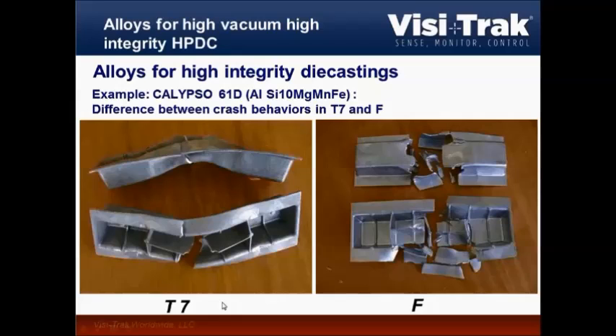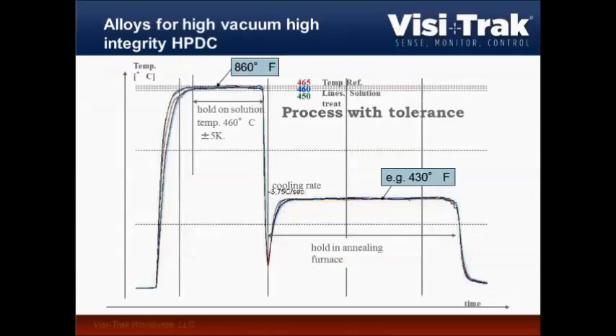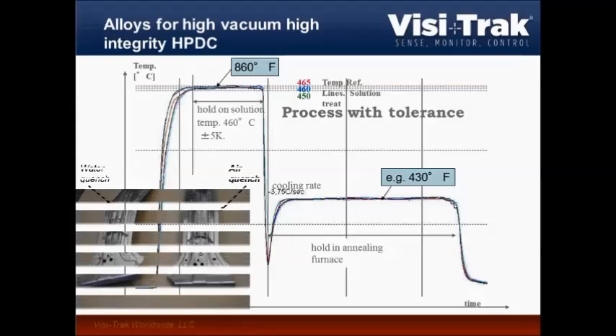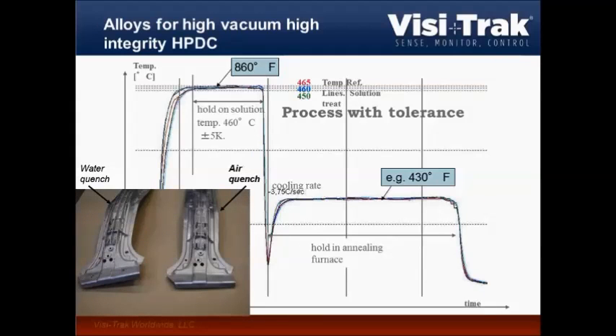They were damaged, but still intact, while the as-cast parts were really scattered into many different parts. So therefore, for safety critical crash relevant parts, it continues to be important that we develop proper heat treatment recipes that include at least partial solutionizing, and as I mentioned before, the quenching after the solution treatment is very critical for our tolerances, and you can see the difference here.